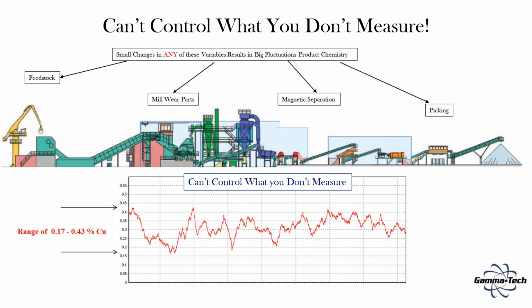operation. Many shredders will talk to you about having multiple pickers on the line. And from our experience, if a shredding operation is throwing humans at the problem, the war is lost. The key to making a high quality, low variability grade of shredded is controlling all of those factors with not a heavy reliance on the manual picking operation. That graph below is what a shredder typically looks like when we turn the analyzer on. That is a typical commercial grade of shredded with an average of about 0.35 copper with a high degree of variability and range.